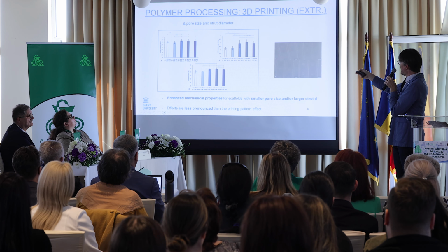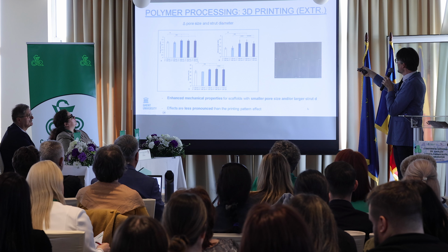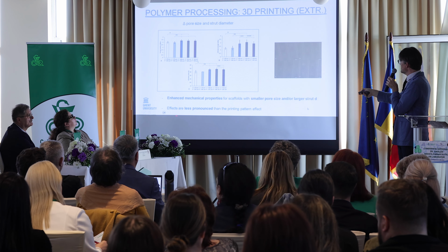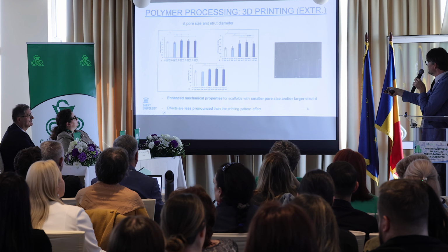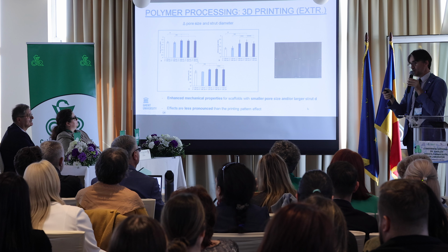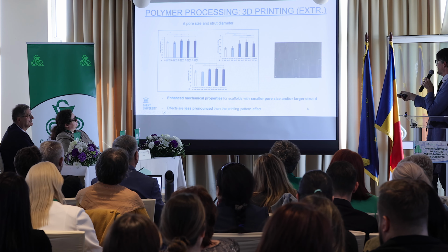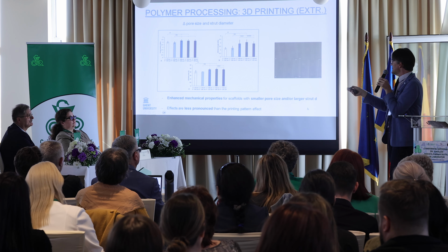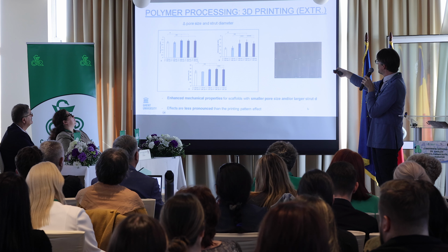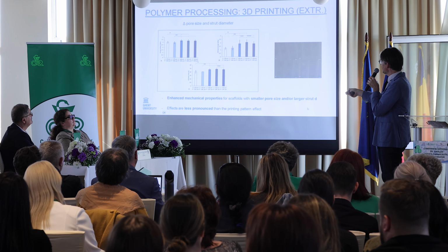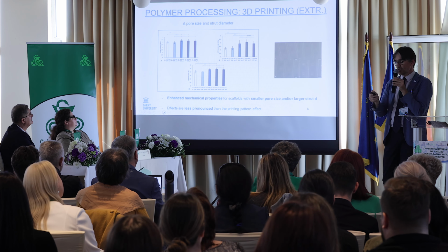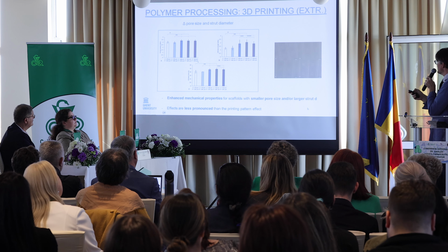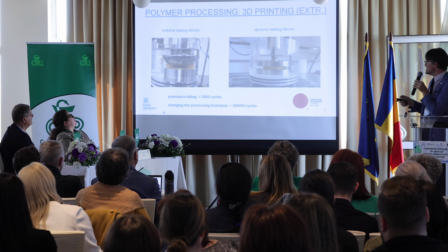Next, we looked at how pore sizes and strut diameters affect the mechanical properties, and much to our surprise, these effects are much less pronounced as opposed to the printing pattern. So whatever you change in this range related to pore sizes or strut diameters, it's mainly the printing pattern that has a real effect on the mechanical properties.